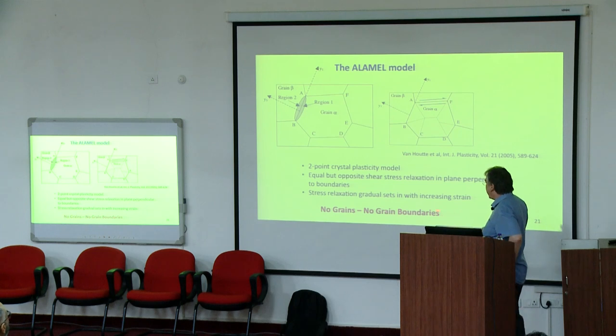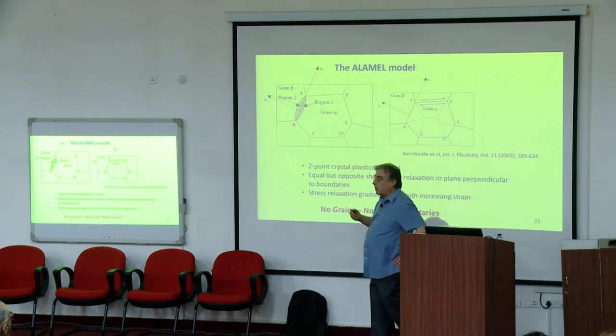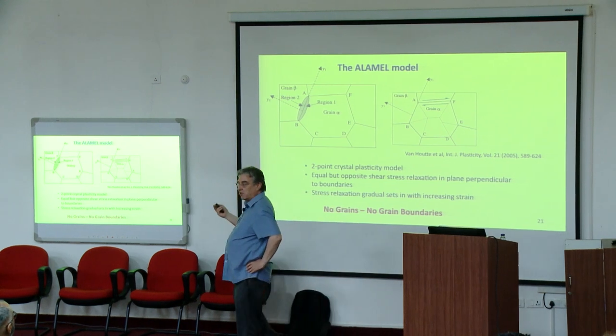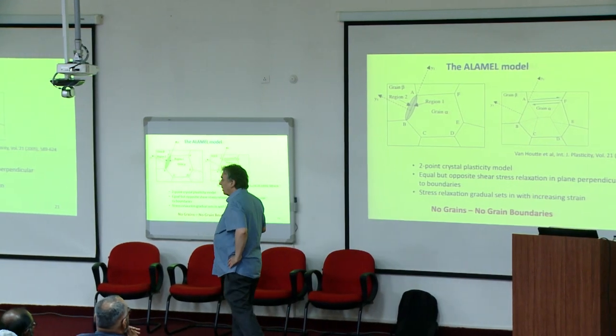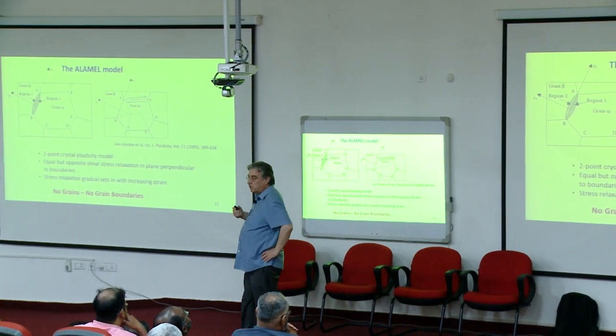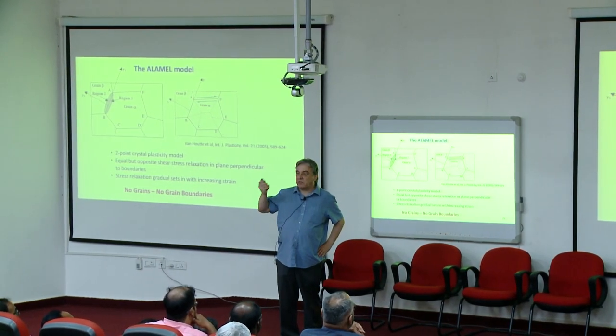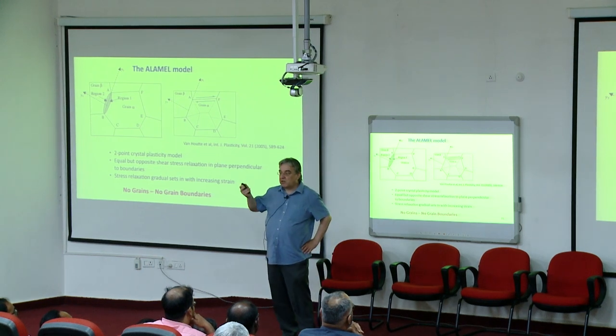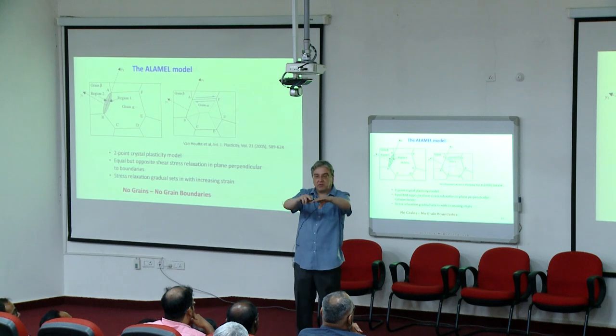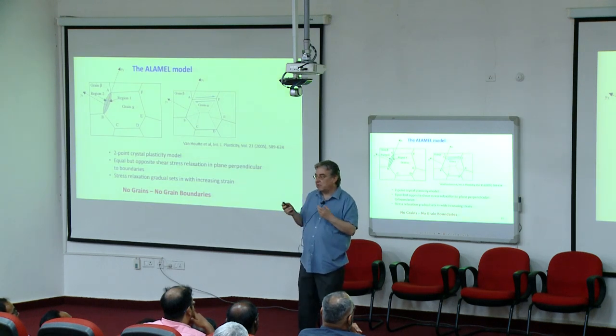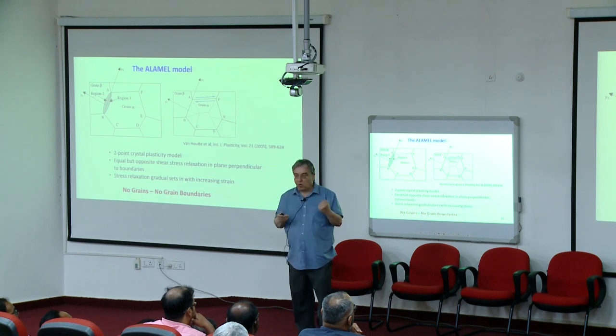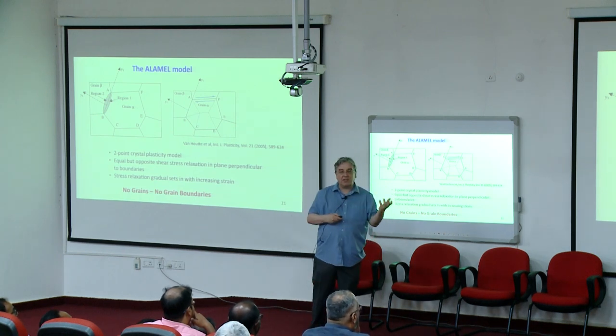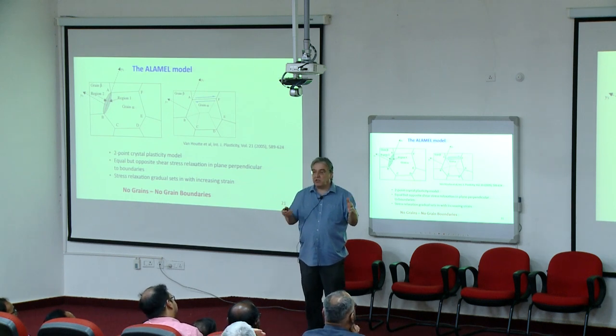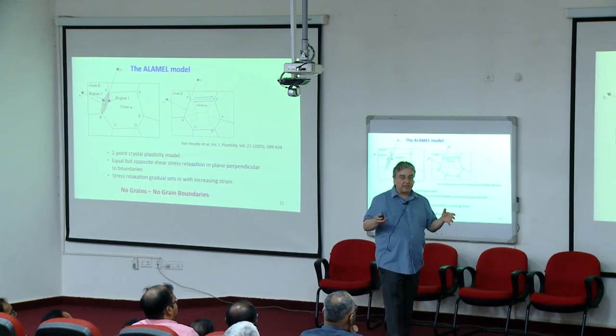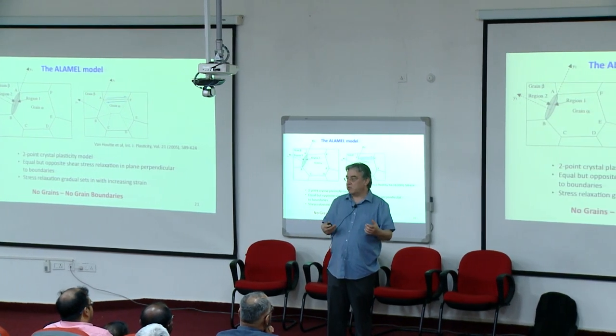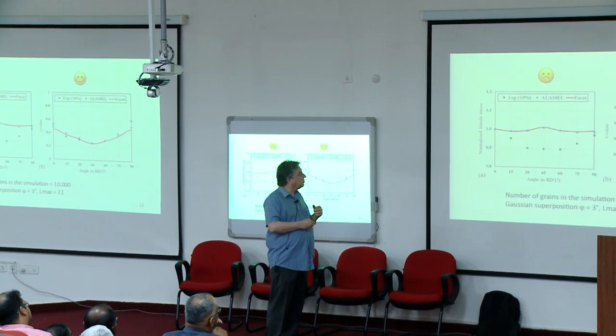The interesting aspect is that it's entirely different from a representative volume element model. We don't consider individual grains. We don't consider grain boundaries. We only consider crystal orientations. The crystal orientation in reality can be divided over many different grains in the material. So there is a conceptual difference. It's a statistical way of dealing with a material. We are going to reduce the material to a set of n different crystal orientations. That's it, and that's what we are going to work with.